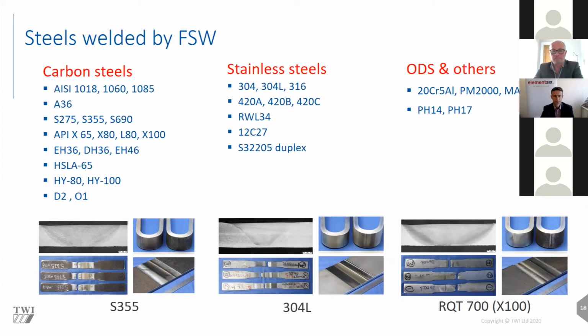We were then asked, can you weld some of the grades of steel that are regarded as being unweldable, such as the oxide dispersion strengthened steels? And again, because we're not melting anything, we're able to do that because we do not destroy the oxides that are in there to strengthen those steels.